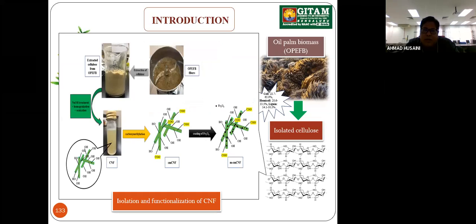So in this study, OPEFB will be prepared and then extracted by a pre-treatment process using sodium hydroxide, and then bleached using sodium hypochlorite before undergoing a chemomechanical process to form cellulose nanofibril. And then it will undergo carboxymethylation, which is divided into two parts, mercerization and etherification, to produce the carboxymethyl cellulose nanofibril, where we replace the hydroxyl with the carboxymethyl group at the C6 carbon of the cellulose. And then we coat it with ferrum oxide using the sol-gel technique.